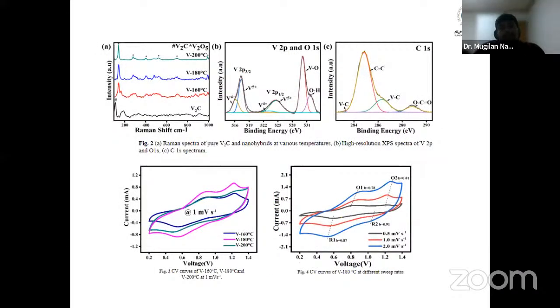Coming to the Raman spectra of vanadium carbide at different heat treatment temperatures: in V180, I found the presence of V2C, and V2O5 is also partially present, whereas in V200, the Raman spectrum is fully like V2O5. In V2C and V160, it is still the same as V2C. So I found that V180 has partially oxidized V2O5 present on V2C.